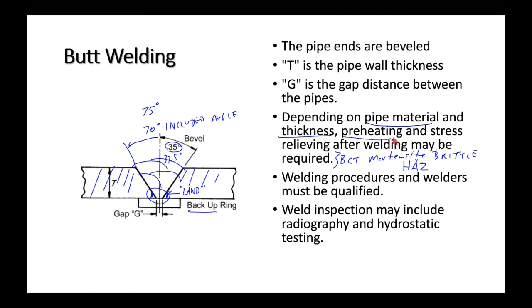So to deal with the heat affected zone, we can preheat the weld joint so that it cools off slowly, because if you recall, when we looked at the iron carbon phase diagram, we had the lower critical temperature, which was 723, and here we have the upper critical temperature, and here we had perlite and ferrite, and here we had perlite and cementite, and we said that it was the rate of cooling that created martensite. The phase change is not permitted to happen at its optimum rate, and instead of the austenite forming perlite, cementite, and ferrite, it forms a body-centered tetragonal martensite. So we have this heat affected zone, and it's all about the rate of cooling. So if we can preheat the pipe, then it cools slower, less martensite formation.